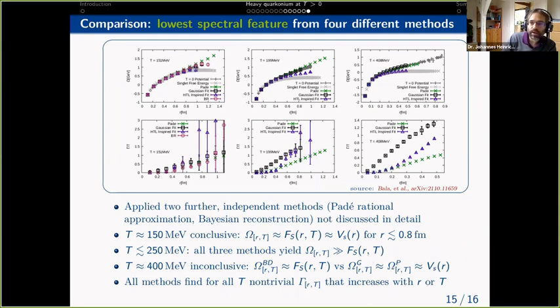Here in dark gray, you have the 0 temperature static energy, in light gray, the singlet free energy, which is screened at roughly 0.8 Fermi. All of these results are essentially consistent with vacuum physics. But you see a finite imaginary part in all of these results, which indicates that here dissociation of the quarkonium state is already at play, even at this very low temperature.